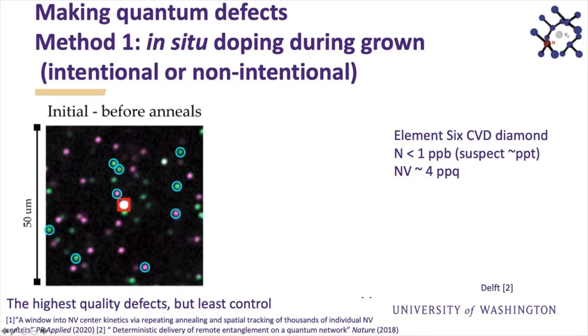And to give you an idea of the types of purities that we're working with in these materials for quantum information applications, this diamond is specified to have nitrogen that's less than one part per billion. But because of the studies that we've done on growth, where we know how many nitrogens are typically incorporated as nitrogen vacancy, I can do this measurement and I can estimate that in this particular sample, we're at the parts per trillion level of impurities. So almost none of this diamond actually is nitrogen, and even less is NV.